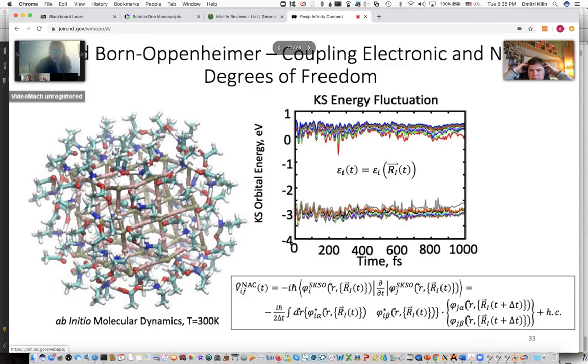So basically it just shows the atoms vibrating, or the nuclei vibrating, for our molecular dynamics trajectory. And then at each time step, the energy of the orbitals depends on the ionic motion, which is the equation in the middle of this figure. So at each time step, the orbitals fluctuate approximately harmonically due to fluctuations of the ions. And so we run our dynamics for 1 picosecond to generate enough data points.